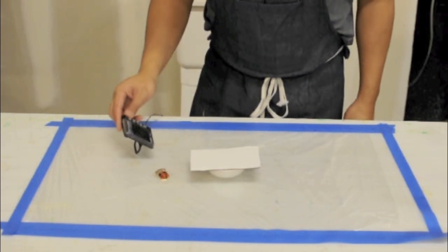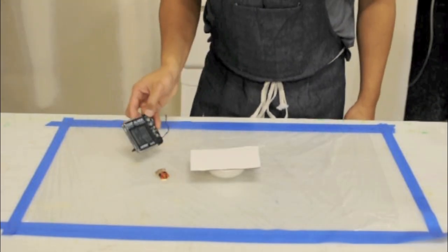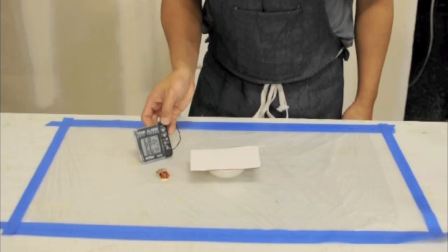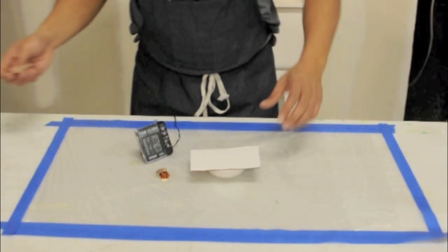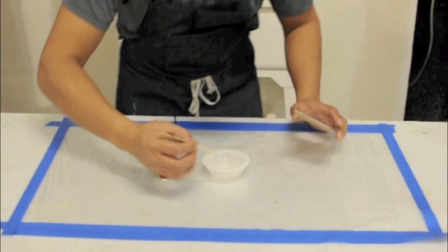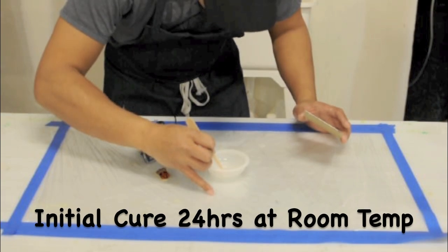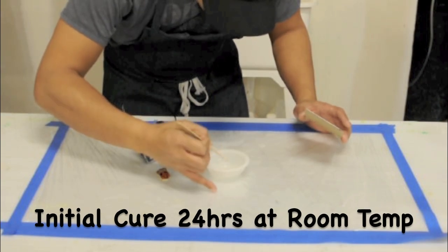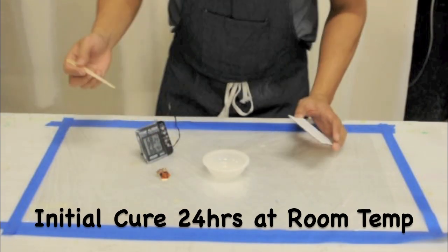It's helpful to know the ambient temperature that you're curing your resin in, and you should avoid working in temperatures less than 60 degrees Fahrenheit. At regular room temperatures, your resin should start to gel within 24 hours. It won't be fully hard, but it should be firm enough to support your embedded object.